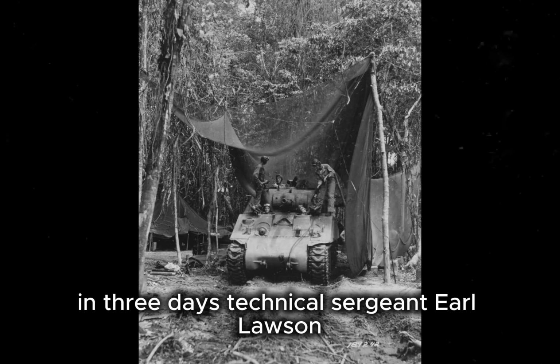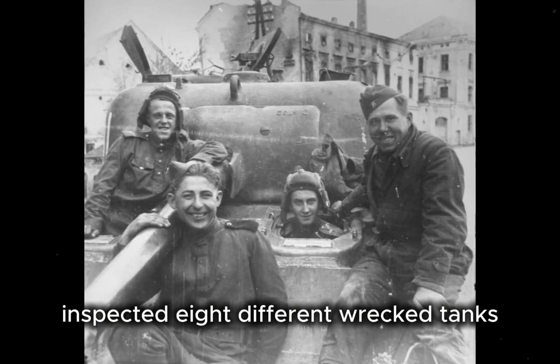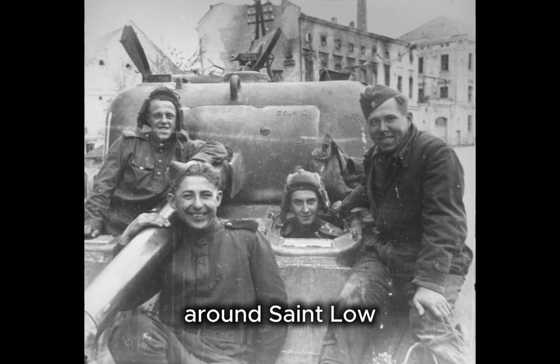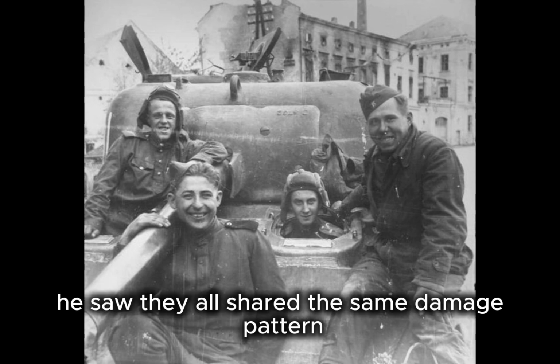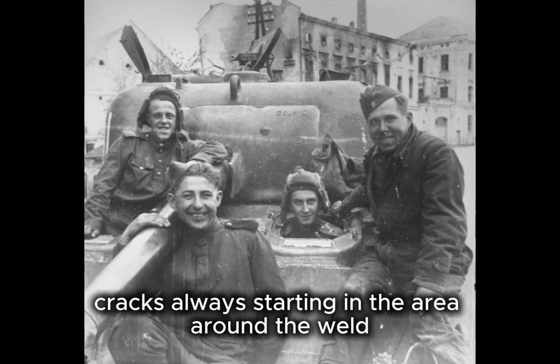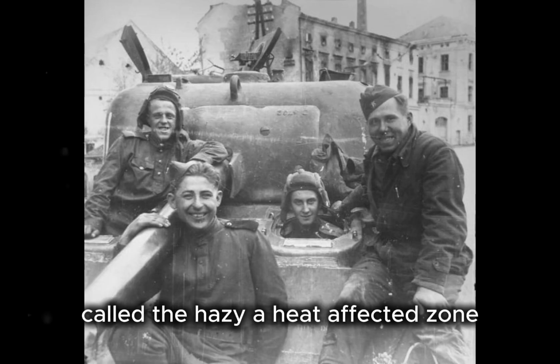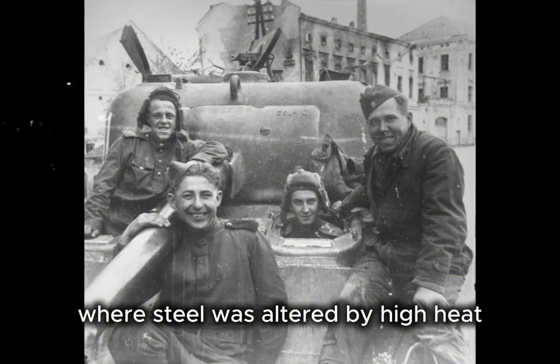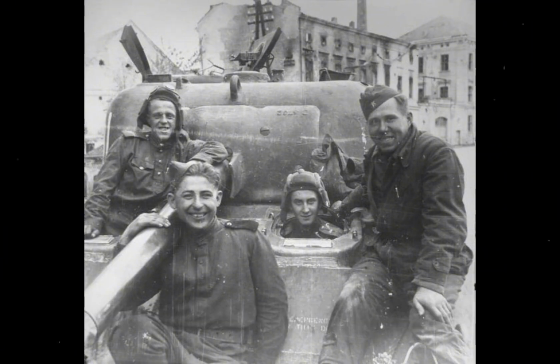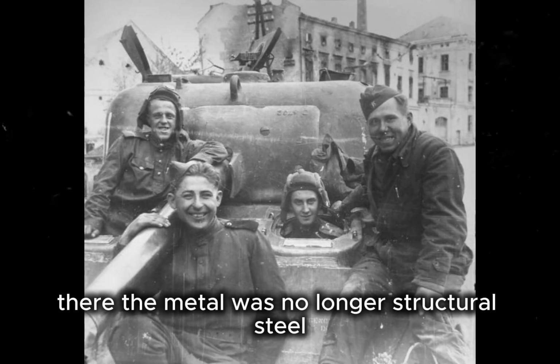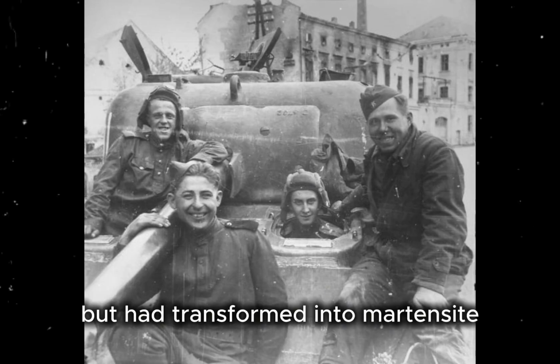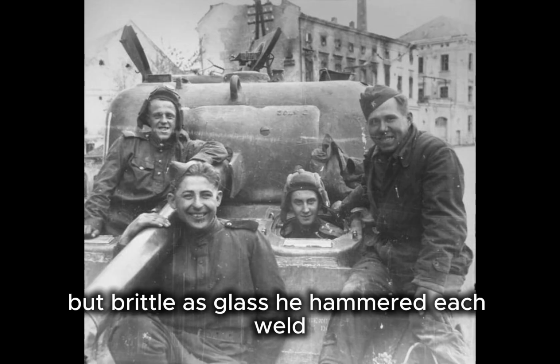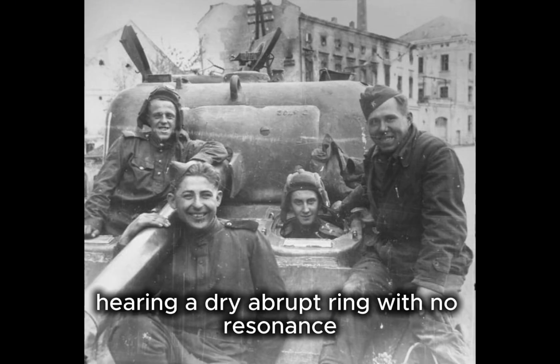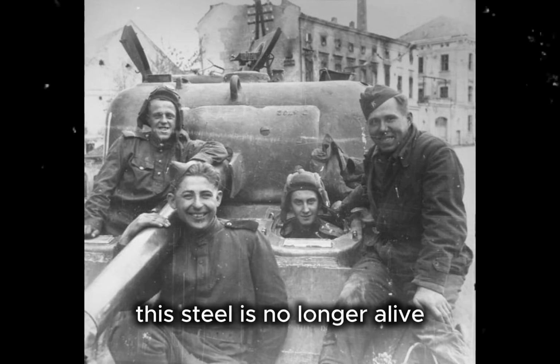In 3 days, Technical Sergeant Earl Lawson inspected 8 different wrecked tanks around St. Lo. He saw they all shared the same damage pattern, cracks always starting in the area around the weld, called the HAZ, heat-affected zone, where steel was altered by high heat, then cooled too quickly. There, the metal was no longer structural steel, but had transformed into martensite, hard, shiny, but brittle as glass. He hammered each weld, hearing a dry, abrupt ring with no resonance. "This steel is no longer alive," he muttered.